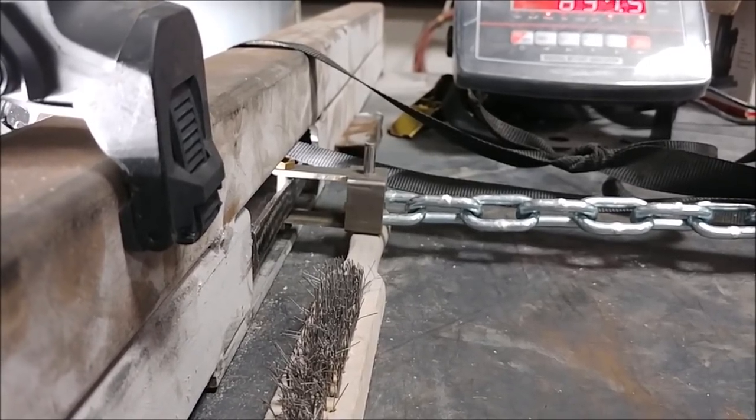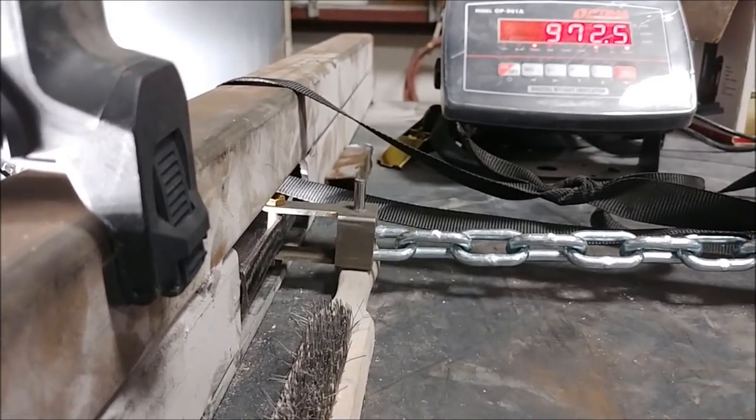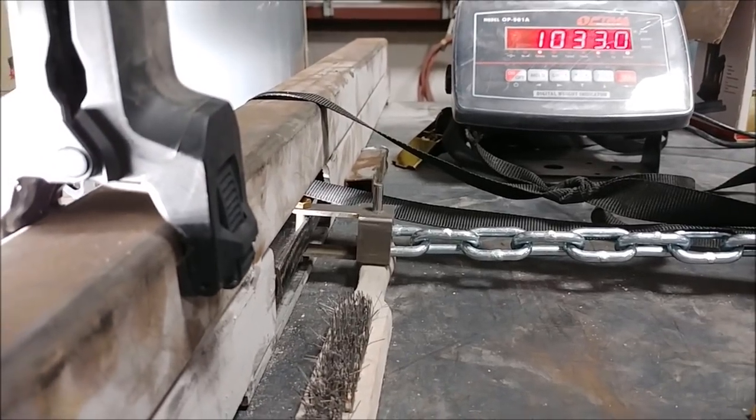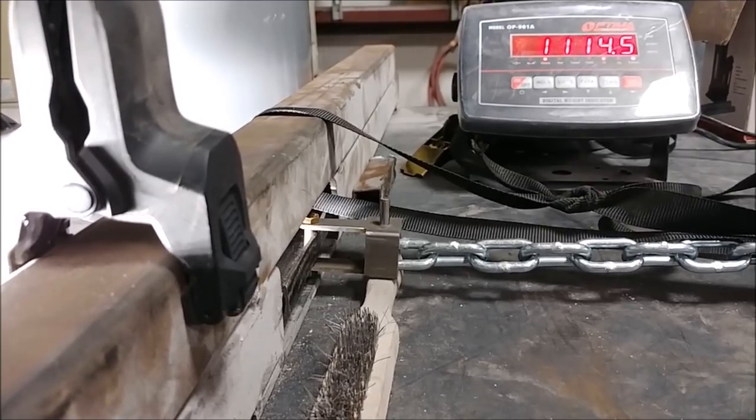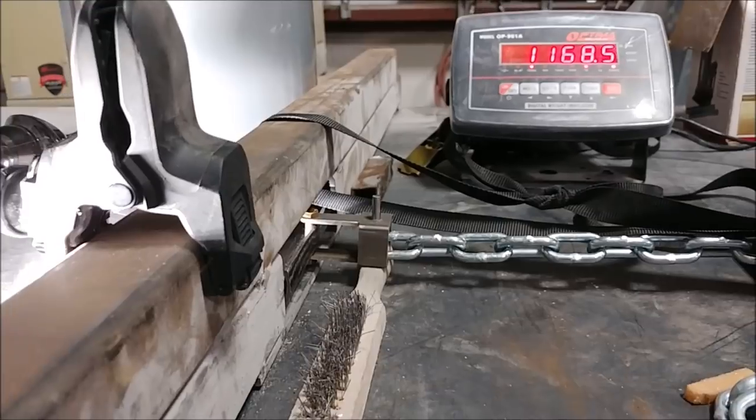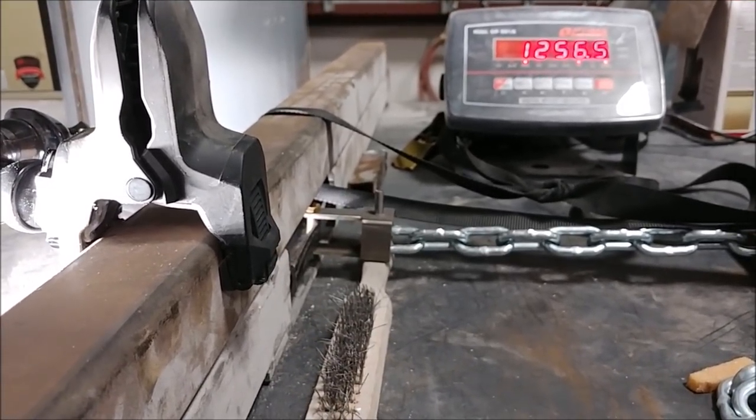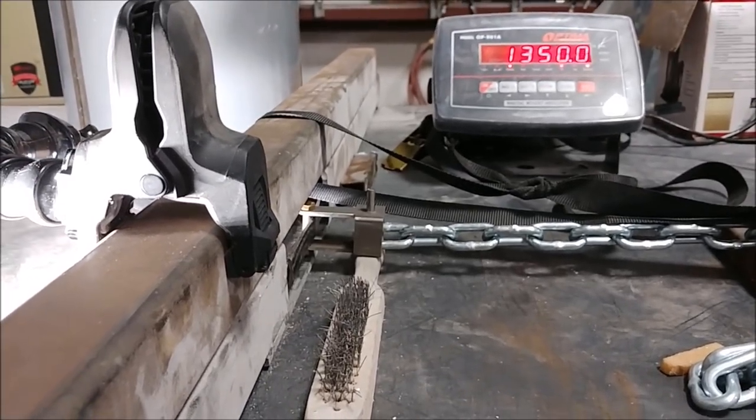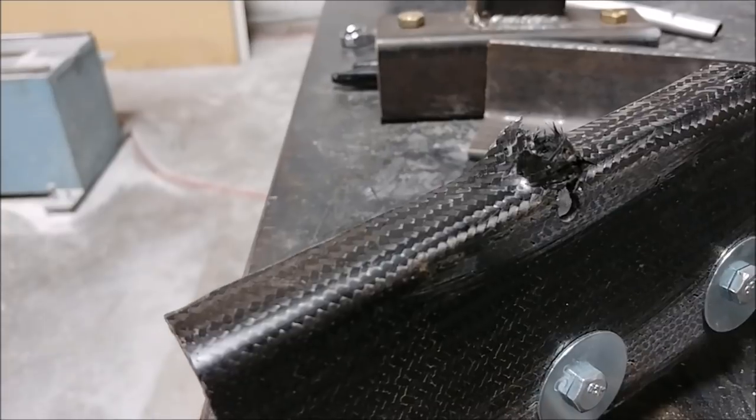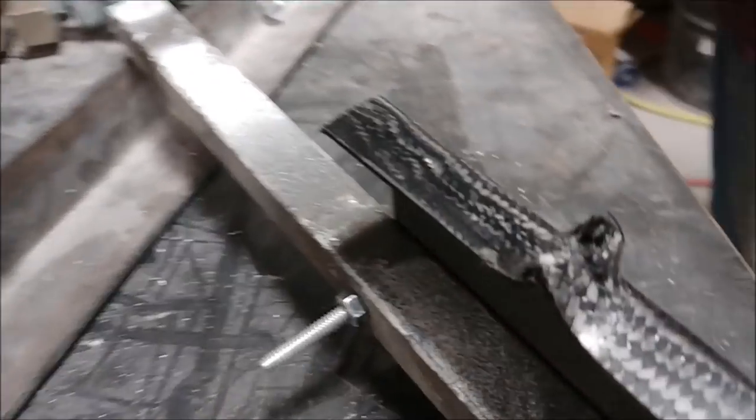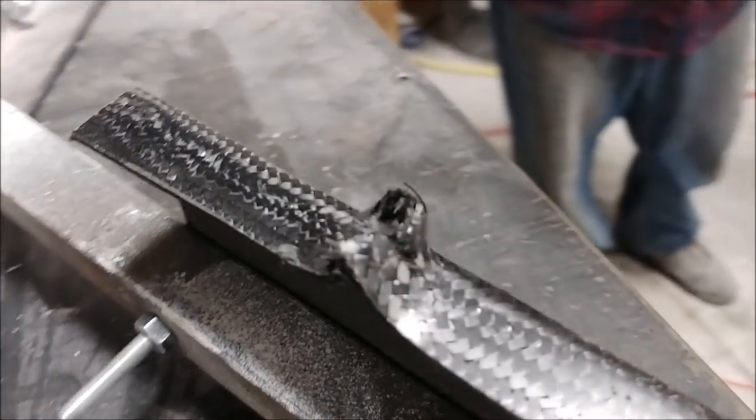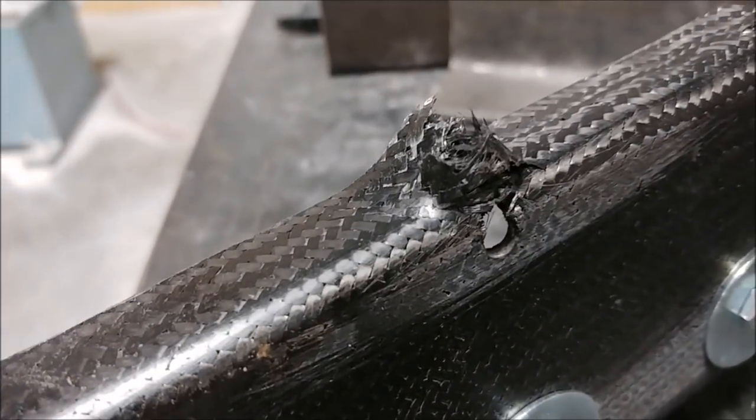It's getting way up there beyond what Mark looked for. Ultimately it went just over 1400 pounds before it gave way. It just pulled through like you'd expect eventually. It's pretty impressive and Mark's super happy with the outcome. Needless to say, I don't think we have any worries about our locks holding the pressurization.